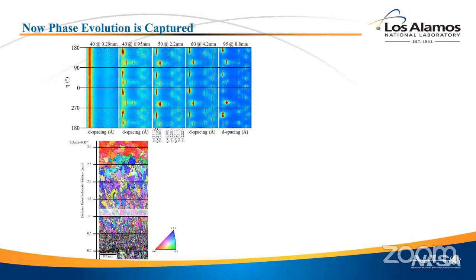If you take those rings and do a polar transform, turn them into rectilinear coordinates, on the far left you see liquid, right? It's a nice broad diffraction beam. That's right at the melt pool. As you come further to the right, you're moving further and further from the melt pool. In some sense, you're moving back in time. You're seeing material where it's been longer since it's solidified. So you can think about it in either way. Again, the spacing as you go down, the way the bright spots are, that's the texture showing up. So instead of being around the circle, now they're in lines. And it might be hard to see from your seats, but I've indexed the two different phases in stainless steel, the austenite and the ferrite.